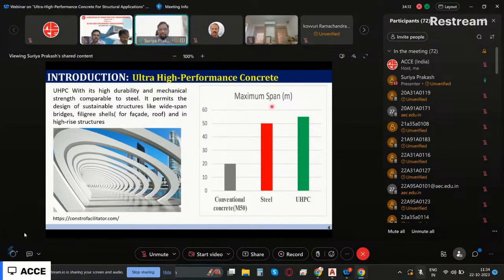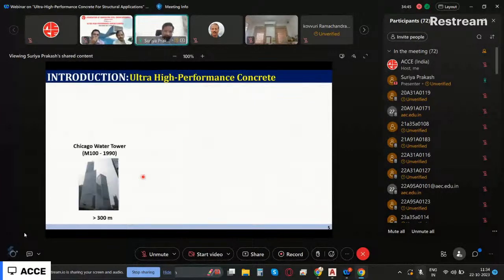Now, if you see here the maximum span, if I'm using a conventional concrete, I can go for 20 meters. If I'm using steel, I'm going up to 50 meters. I'm just saying one example. With UHPC, you can go even longer because now I can put pre-stress also. So these are some of the advantages, and you can make very complex structural shapes. That's why, in fact, facade elements are now being made using UHPC. You can make a very thin, nice facade element, and that facade element is always in contact with water and the external environment. So that is again a big advantage.